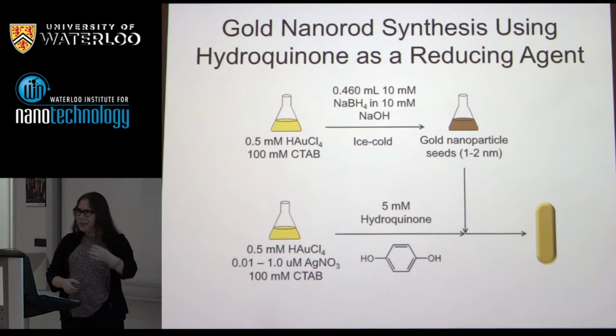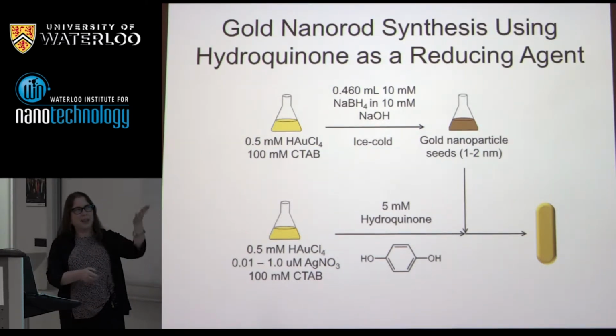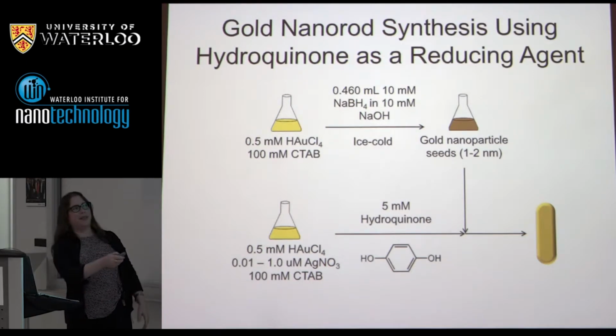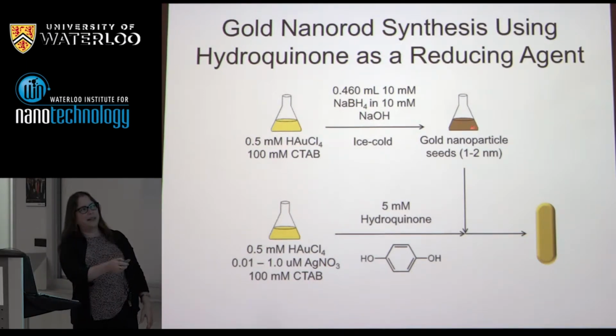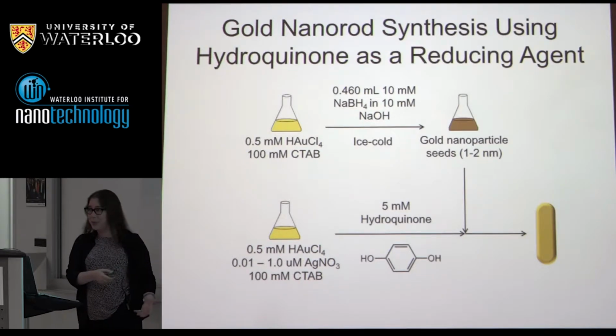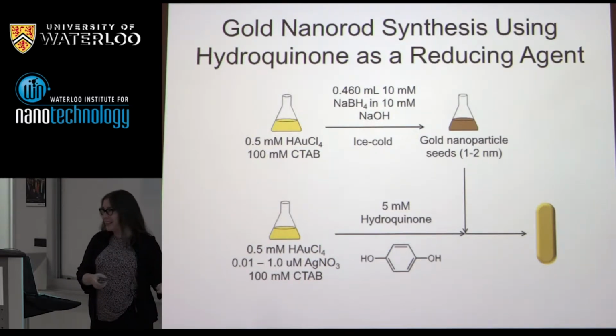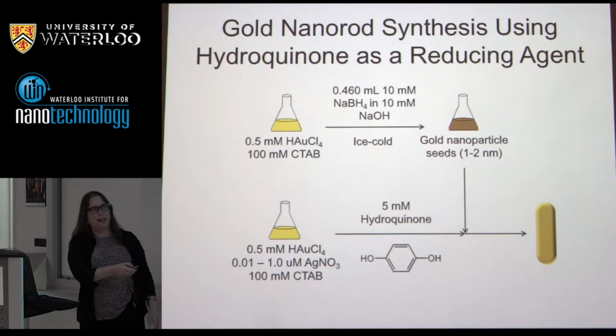So I'll just tell you, though, that even though we've learned how to do this pretty well for a while now, we keep improving things. So here's a slightly different prep. If you want details, quantities, here we go. So here's making the seeds. Okay, you can change the pH. That does change things, etc. And then now, what's the difference? The big difference is the weak reducing agent, not ascorbic acid, it's hydroquinone. It has a different redox potential, but kind of so what. And our tuning of the aspect ratio comes from tuning in this range of silver nitrate concentrations.